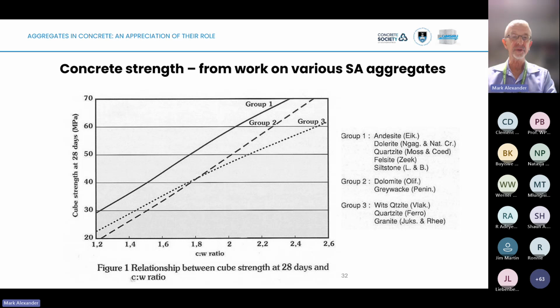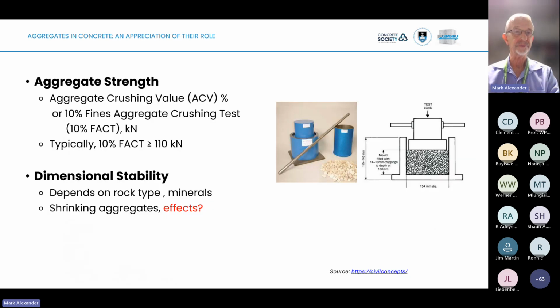Of course, you have to have these aggregates available. It doesn't mean that they're all available in every area. When it comes to aggregate strength, obviously, we are working with the material in its granular form. We can take rock samples or rock cores and test the unconfined compressive strength, but usually we test this in an indirect way through either the aggregate crushing value or the 10% fines aggregate crushing test. Essentially, you take a sample of graded aggregate, a certain grading and a certain mass, you put it into the steel cylinder, and then you really just crush it under a loading machine, and either measure the percentage fines that you create or the load to give you a 10% fines value.